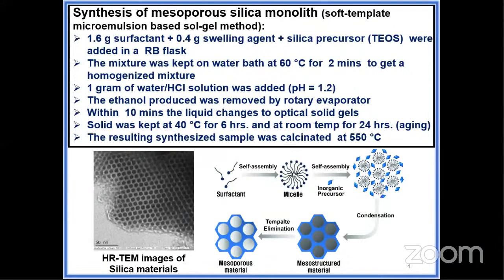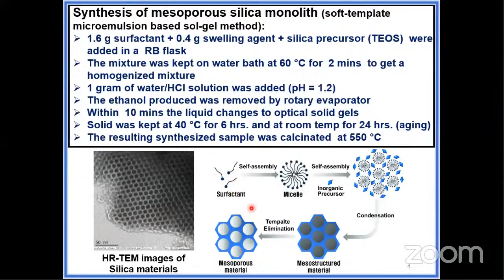For the synthesis of mesoporous silica monolithic material, we have used a soft-template method. We have taken P123 as the surfactant templating agent and TMB as a swelling agent. TEOS we have taken as the silica precursor. Under proper aging and calcination conditions, we obtained the mesoporous silica monolithic material. This is the general mechanism involved in the preparation of silica monolithic material: a surfactant forms a micelle at a critical micellar concentration.